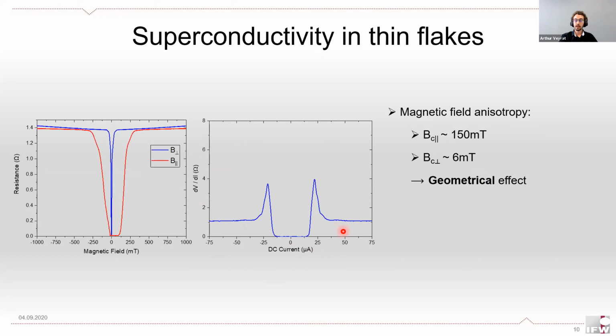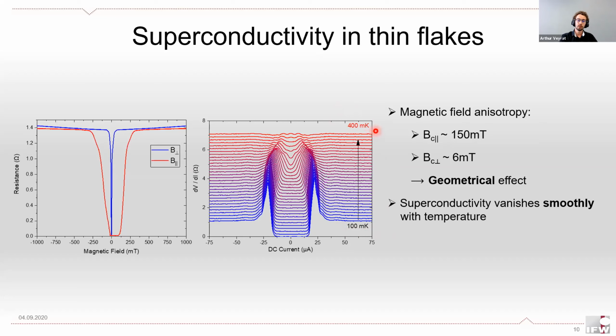This measurement was made at base temperature, but we also made it for a range of temperatures up to temperatures above the critical temperature. All the curves are shifted vertically for visibility. And you can see that with increasing temperatures, the hallmarks of superconductivity, that is the zero resistance state, as well as these differential resistance peaks, smoothly vanish and disappear at higher temperatures. So this is a good proof that we have superconductivity in our exfoliated structures.